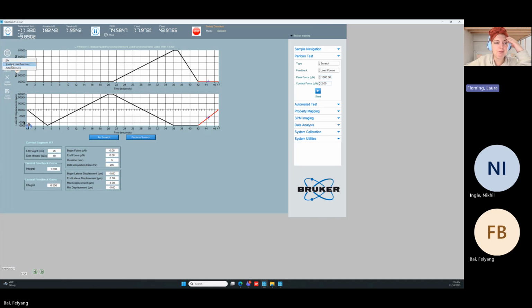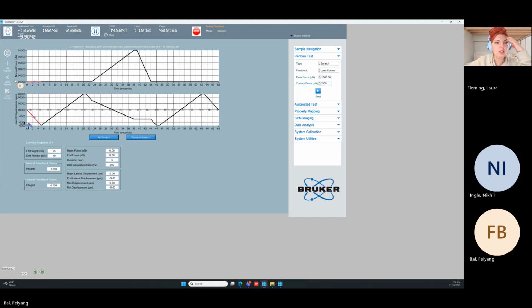When you add the retrace segment, you get this extra portion, this extra 20 seconds at 0 micronewton. What's happening here is that you're doing the trace again, only it's after the scratch. So you're tracing over where the scratch is. You trace so you can do the tilt, then you do your scratch, and let's say you're really trying to dig out some of the material, to make a deep well for some reason. Then after the scratch is done, you unload, but then you trace along it again, and that tells you how deep that trough is. So you have the normal displacement before and after the scratch to tell you how much that normal displacement changed, to tell you how much sample you wore away.